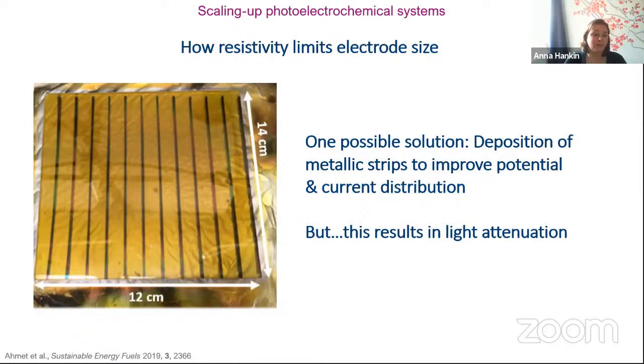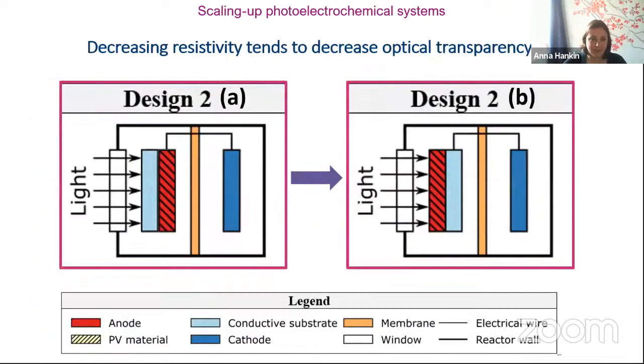So what about if we give up on the transparency completely? What happens then? Well, if you take a non-transparent substrate, so for example, let's say you replace fluorine-doped tin oxide on glass with, let's say, titanium or something, it means that you can no longer irradiate your semiconductor through the back, and it means that you have to reorientate your electrode such that the light-absorbing part faces towards the outside of the reactor so that light hits it directly. Okay, right, so the resistivity of the substrate problem is solved, but you then run into another problem to do with resistivity, but this time on the electrolyte side.